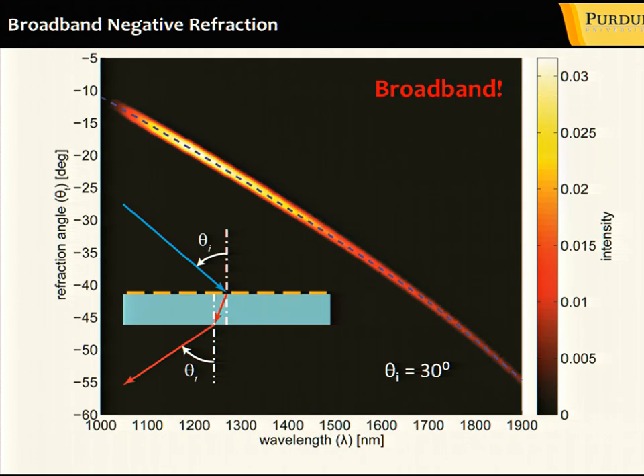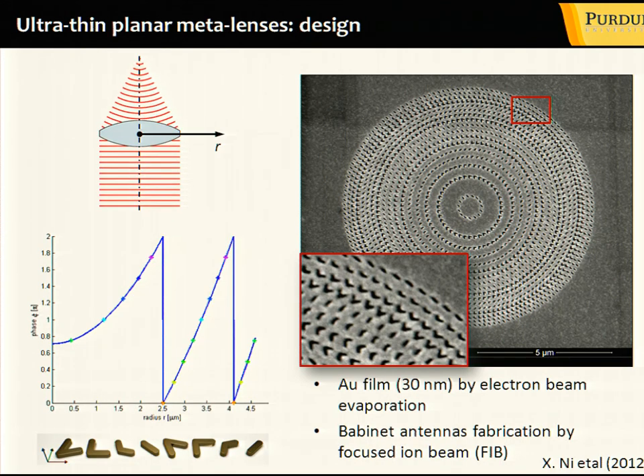Same with reflection. You could send it in any direction. And this is a broadband, very robust effect. We showed that it occurs between 1 to 2 micron. It's not an exotic effect. It's a very broad effect, broadband, and very robust. Which opens up a number of interesting applications, such as, for example, the spatial light modulator used in all TV sets, which could be made extremely thin, much smaller than the wavelengths. In our case, for example, this array of antennas is 30 times smaller than the wavelength.